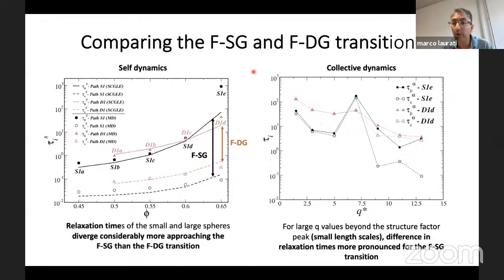And so one can compare a bit more quantitatively the two transitions, both in terms of the self-dynamics and the collective dynamics. In terms of the self-dynamics, this was done by looking at the relaxation time of the correlators as a function of the increasing total volume fraction of the system. And you can see clearly that when we approach the transition at the largest packing fractions, the decoupling of the slowdown between the large and small particles is much more pronounced in the fluid to single glass as compared to the fluid to double glass. So there is a clear quantitative and qualitative difference.